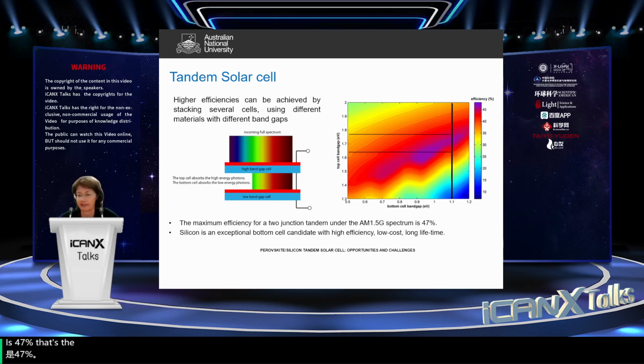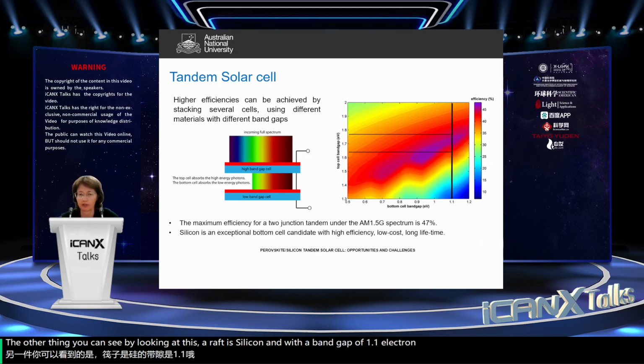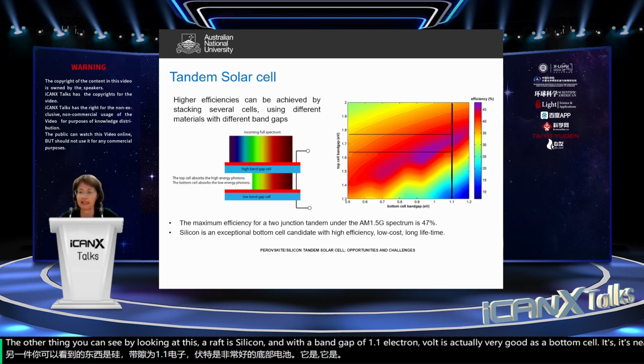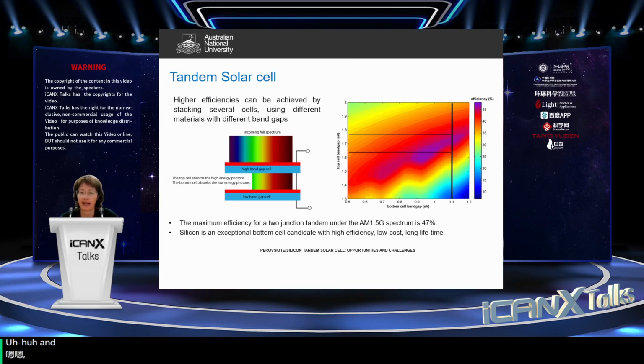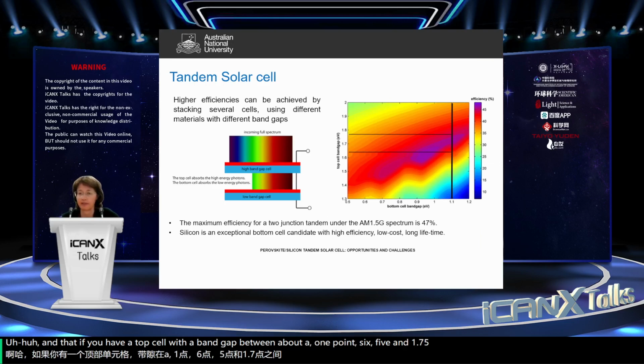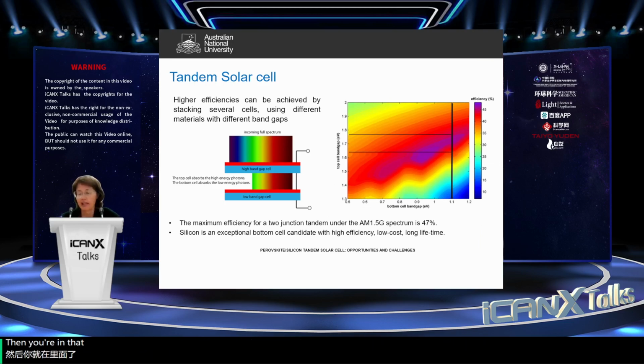That's the theoretical efficiency. The other thing you can see by looking at this graph is that silicon with a band gap of 1.1 electron volts is actually very good as a bottom cell. It's nearly ideal. And if you have a top cell with a band gap between about 1.65 and 1.75 electron volts, then you're in that region where you can potentially get very high efficiencies.